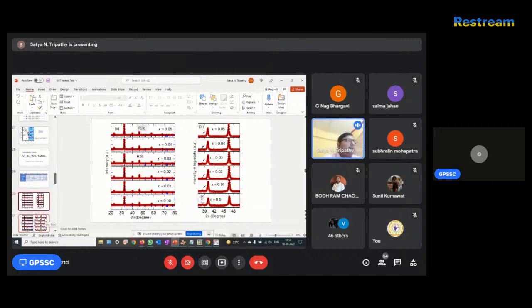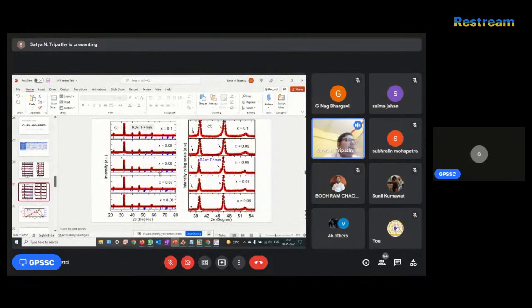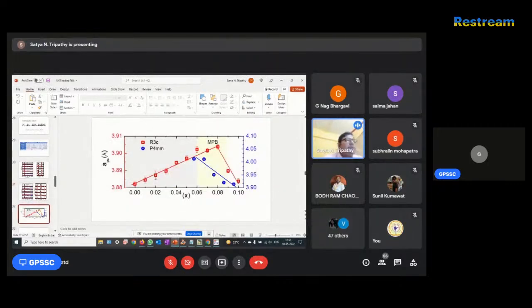But after, I go to the next slide. After 0.06 we obtain new peaks appearing, new phases appearing. So this is the peak of barium titanate. So we fitted with R3C rhombohedral plus P4MM tetragonal space groups. Okay. So these are the refinements we have carried out, and this is the graph we obtained.